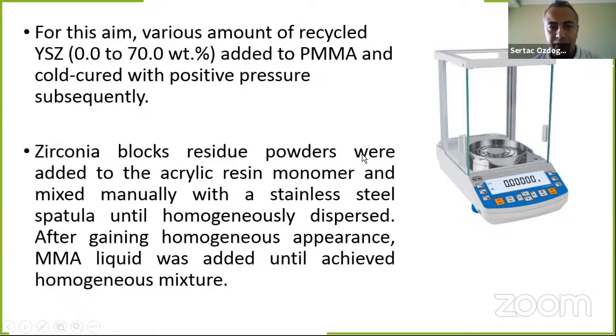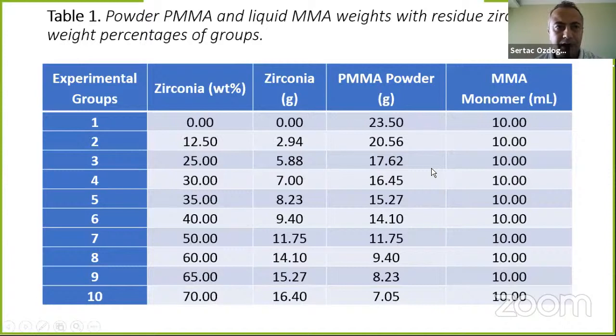Zirconia block residue powders were added to acrylic resin monomer and mixed manually with a stainless steel spatula until homogeneously dispersed. After gaining homogeneous appearance, methyl methacrylate liquid was added until achieving a homogeneous mixture. In table 1, we can see the powder polymethyl methacrylate and liquid methyl methacrylate weights with residue zirconia weight percentage of groups. We added zirconia powder at 10 groups and weight percentages for testing.